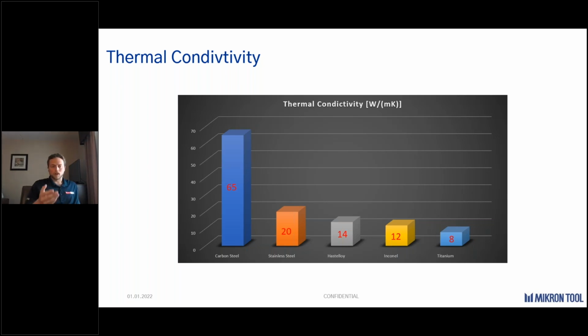Looking at this graph, right, carbon steels have very nice thermal conductivity. When it comes down to it, they like to take a lot of heat. Stainless steels and high temp super alloys, as we're moving into that, have a little bit less, but even compared to the high temp super alloys, titanium has a lower thermal conductivity, right? What this means is it really doesn't want to take heat. It wants to maintain a constant temperature.